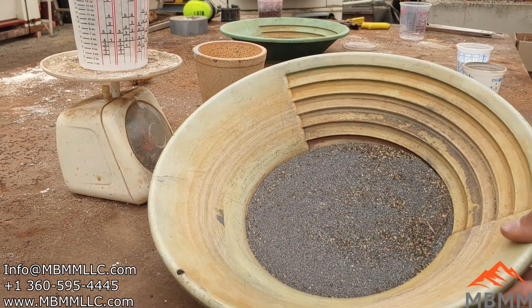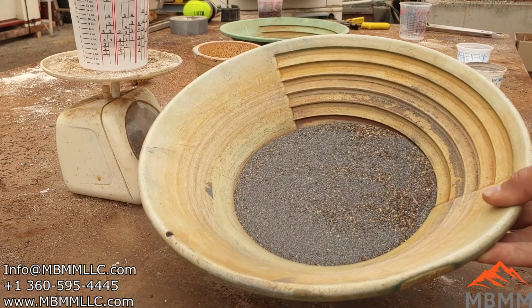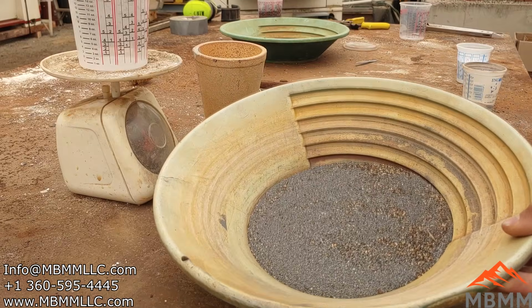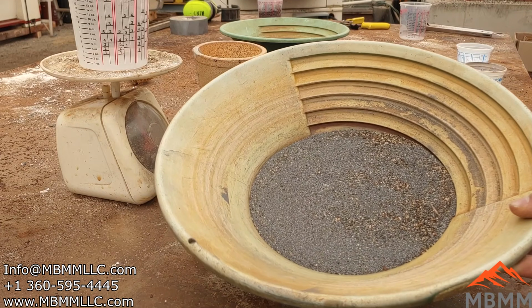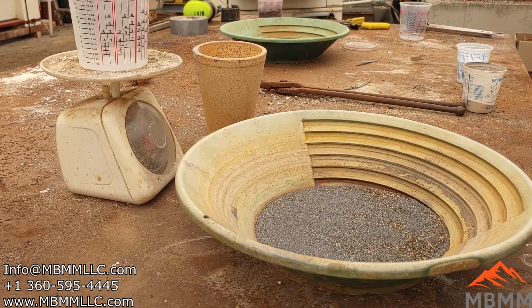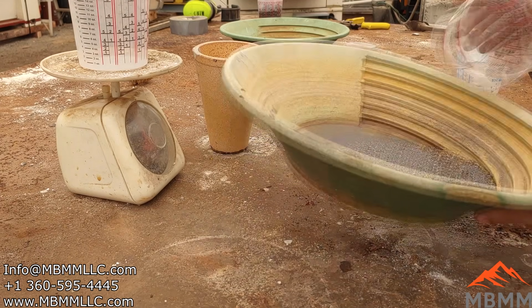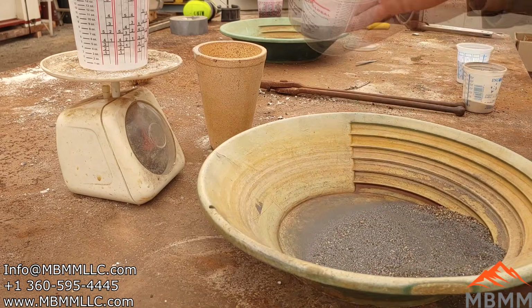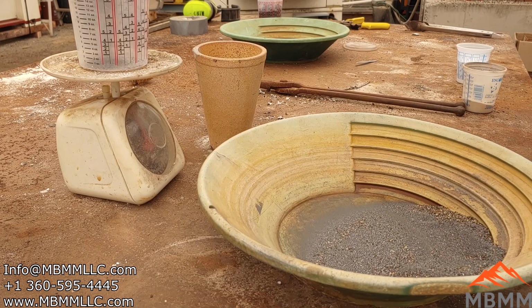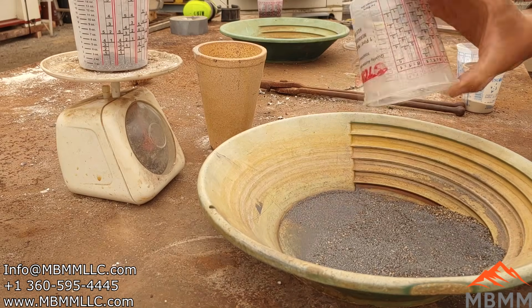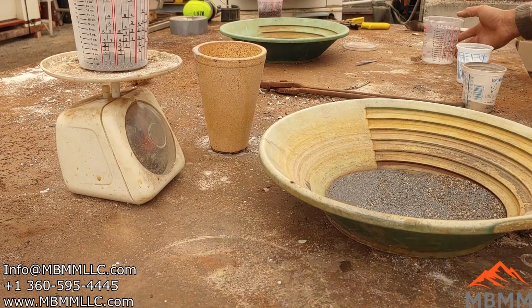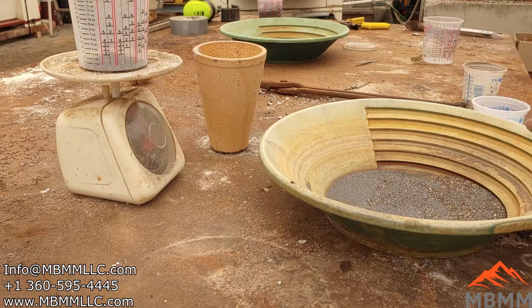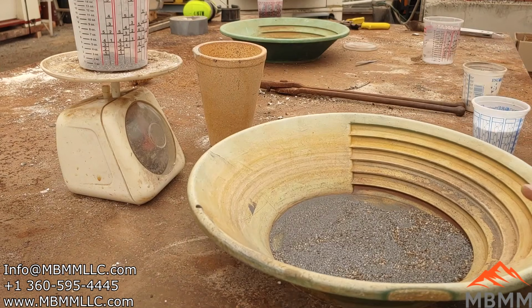Okay, I'm going to weigh out for this first little test 50 grams of the galena. I'm going to add 150 grams of soda ash, and I'm going to add 50 grams of silica. And then we're going to add some iron to help reduce the galena in here to lead metal.